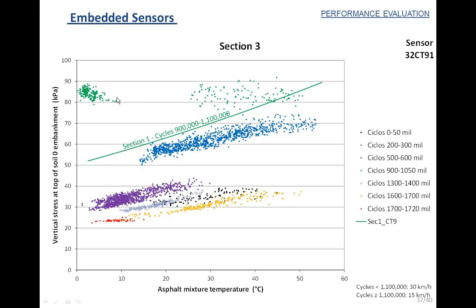And actually, after the reparation of the section, we repaved this section and we put a new material which was stiffer than the original asphalt layer. When we rebuilt section number 3 in cycle 1 million, we just removed the asphalt layer which was highly cracked, and then we put another asphalt material whose stiffness was relatively high. And now we saw a very clear decrease of the stress level that you can see here with this family of points, red points or the orange points.